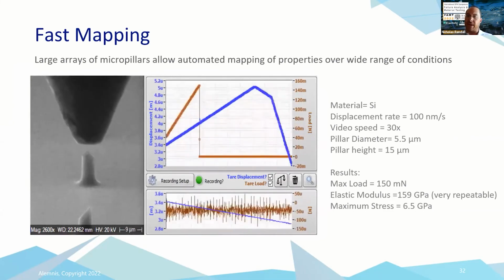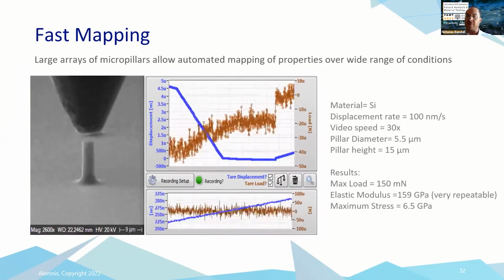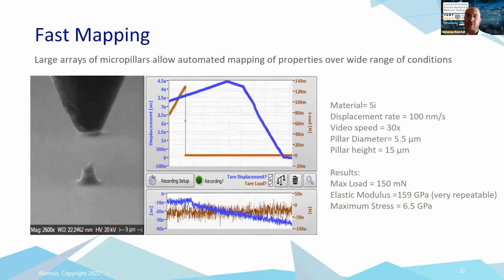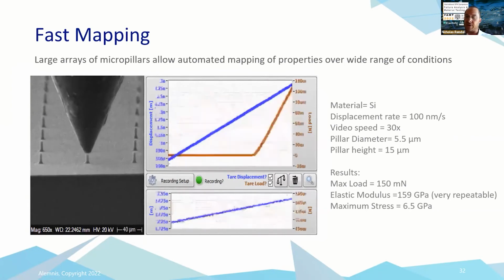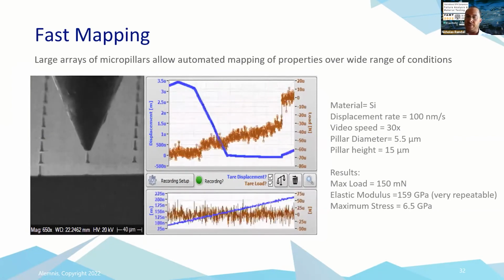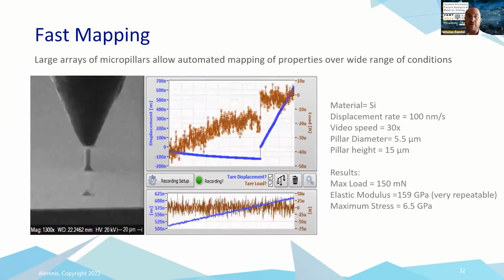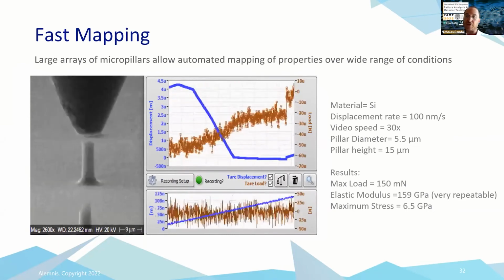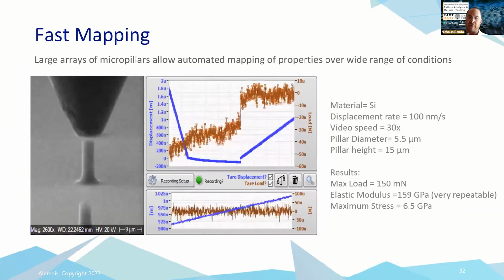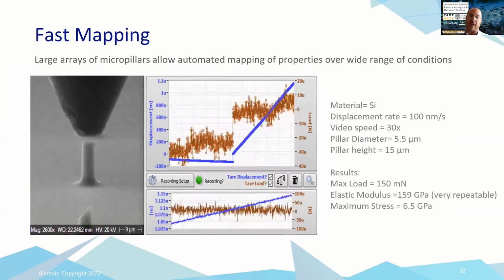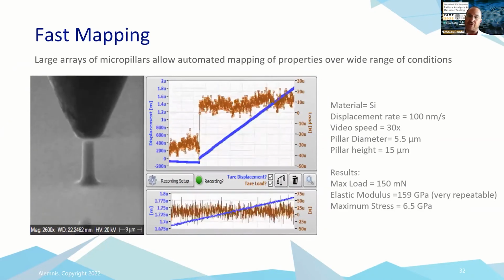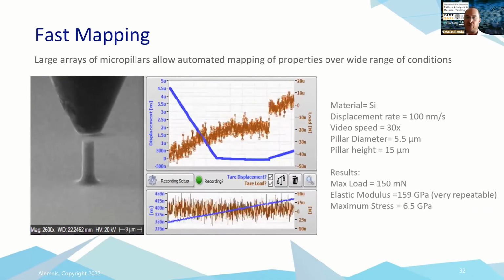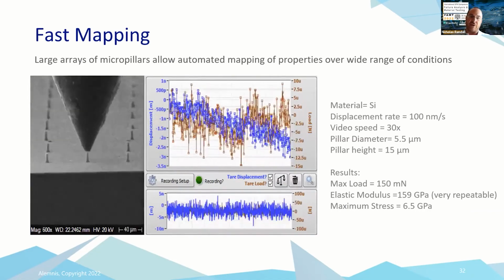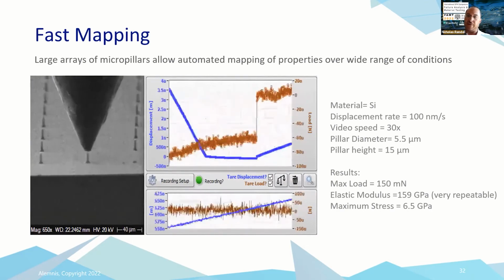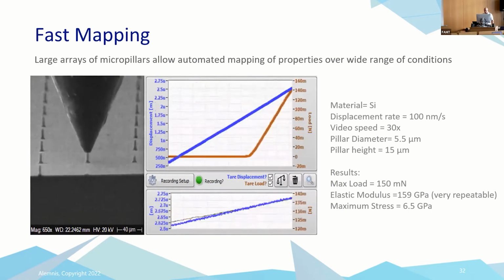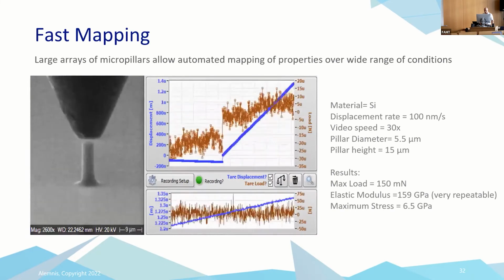But we can basically make any shape indenter and a wide range of materials. We can make the indenters conducting, non-conducting, doped. And that's why we also developed the combination of AFM, so that we'd have the advantage of AFM imaging with the mechanical properties dedicated test. Because with AFM, of course, you can measure mechanical properties, but it's difficult to know the exact tip area shape in order to get the mechanical property in a quantitative way.